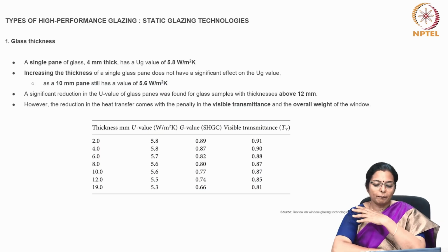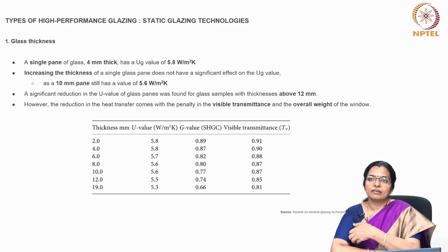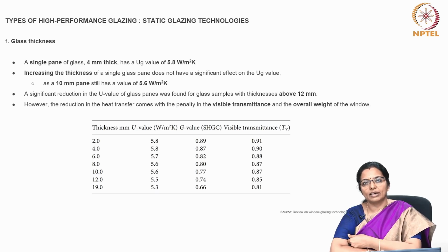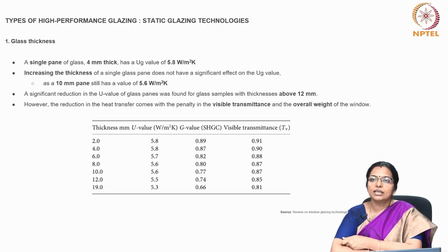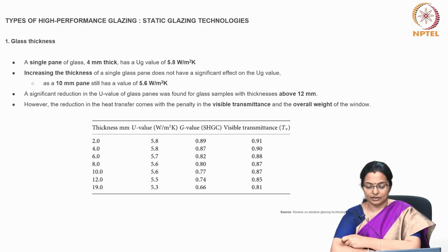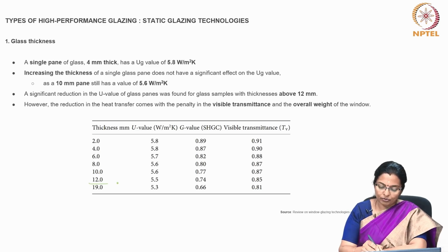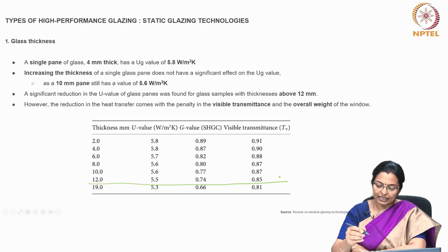Now, a single pane of glass which is 4 millimeter thick has a U value of 5.8 watts per meter square Kelvin. Increasing the thickness of a single glass pane does not have a significant effect on the U value, as a 10 millimeter pane still has a value of 5.6 watts per meter square Kelvin. A significant reduction in the U value of glass panes was found for glass samples with thickness above 12 millimeters. So, only above 12 millimeters, there is a significant difference.